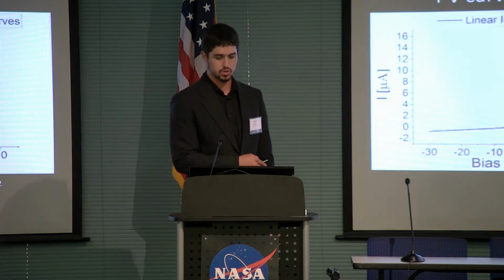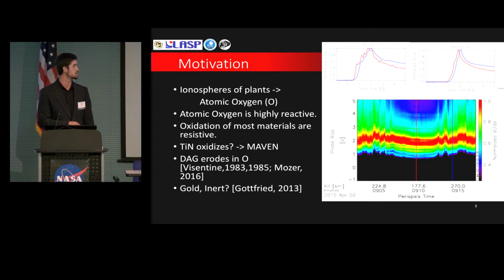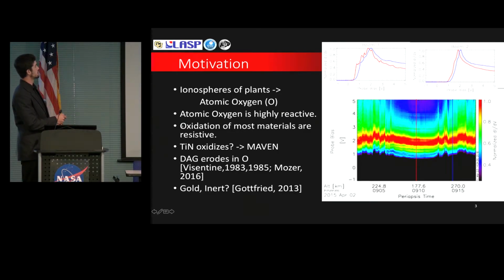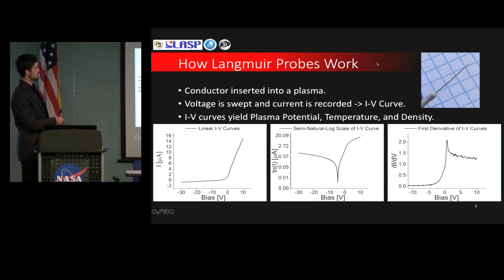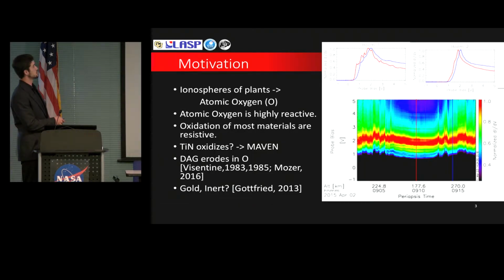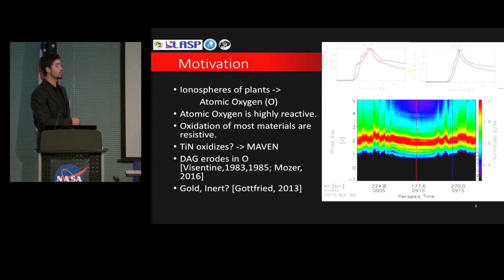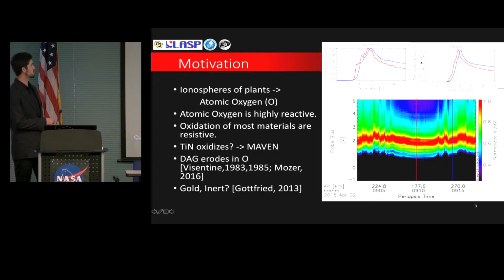However, it's been shown recently that these probes have issues when exposed to oxygen-rich space environments. Specifically in MAVEN, we can see here degradation of the probe after long exposure times to oxygen. This should have looked like this curve to the far right, but instead you can see it is much more noisy. So in the upper atmosphere of planets, the ionosphere specifically, we all know that molecular oxygen is highly reactive, but atomic oxygen even more so, and is thought to be created by photodissociation of diatomic molecular oxygen into atomic oxygen.